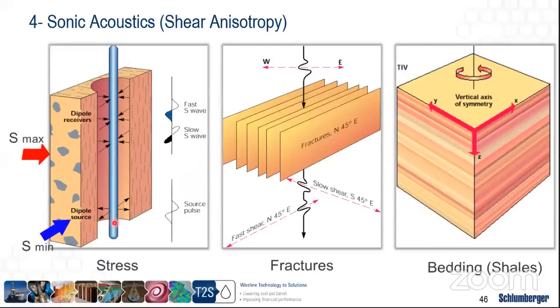But anisotropy does not primarily happen due to the maximum horizontal stress and minimum horizontal stress. It can also happen due to fractures, as well as bedding, such as shale. In order to identify if the anisotropy is really related to stresses or the effect of fractures or bedding, we need to start integrating the acoustic and anisotropy results with wellbore imaging that will be shown later. In order to see if it's really the effect of bedding, which comes into shale, that will be evident on the wellbore imaging as thin laminated sands or thin laminated layers, or whether it's just coming from the stress regime that we have in place downhole that's creating a maximum horizontal stress and a minimum horizontal stress.